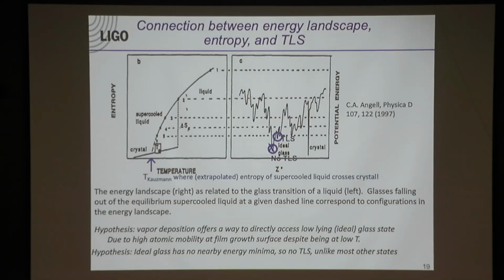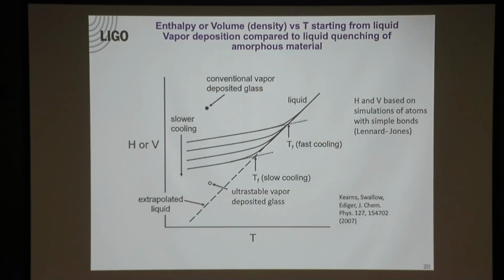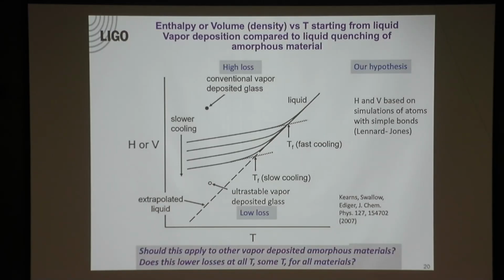But vapor deposition has this very unique feature of the surface. When you're growing a film by vapor deposition, you can grow at a temperature a little bit below the glass transition temperature, where the liquid would long since have fallen out of equilibrium. You can be at that temperature and still have tons of surface mobility. So the atoms at the surface are able to equilibrate and find that low-lying state, which is the whole point. And when they find that low-lying state, it is a higher density state, a lower energy state, a lower entropy state, and it has no tunneling states. I have another diagram to show it, but we'll just keep going.